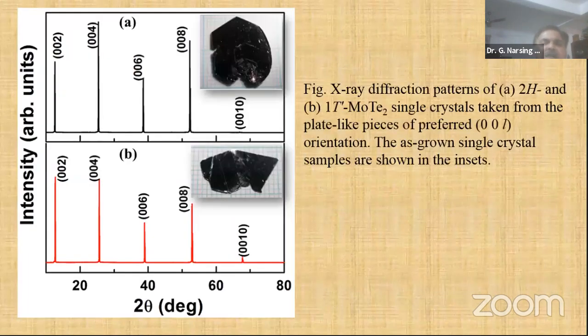You can see now the X-ray diffraction pattern of 2H and 1T prime. How can we recognize them? Both are similar, is it not? Both structures are the same, except this 0010 intensity is a little bit higher here, and it is not there in the other, but the remaining things are identical. This is a single crystal. If you mix the single crystals together, they are both the same. Then you just grind it and make a powder diffraction.